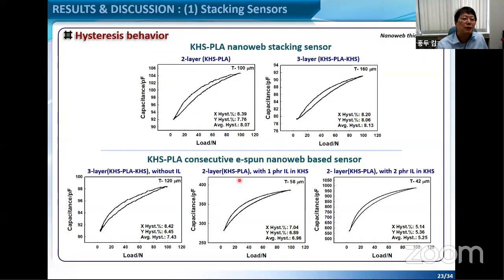If you look at that hysteresis behavior, then it's out of this whole system. Let's say with the 2 phr included the ionic liquid, that it has the best, but it's more likely about 5 to 8%.